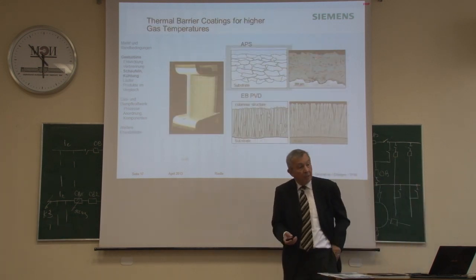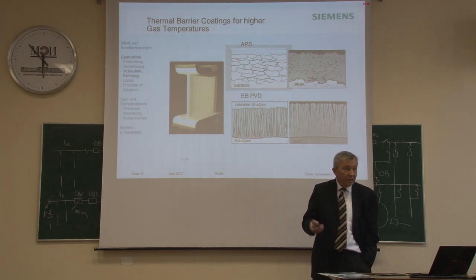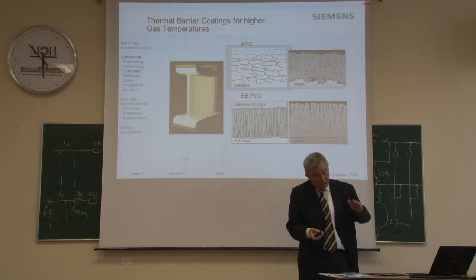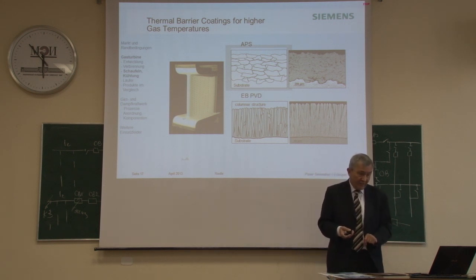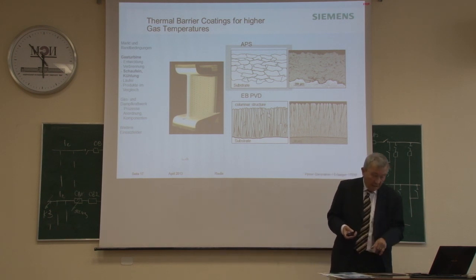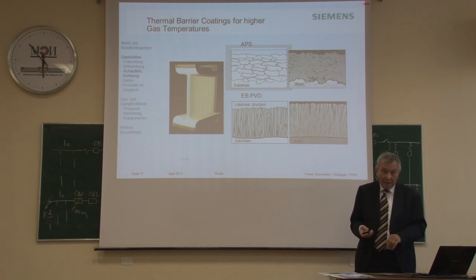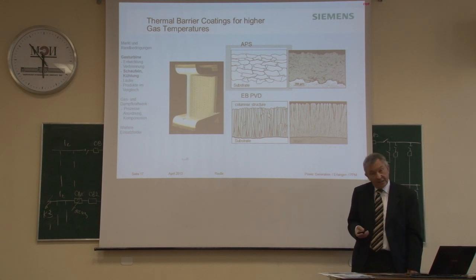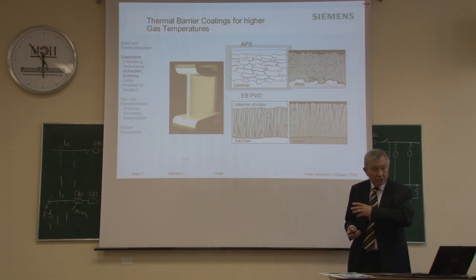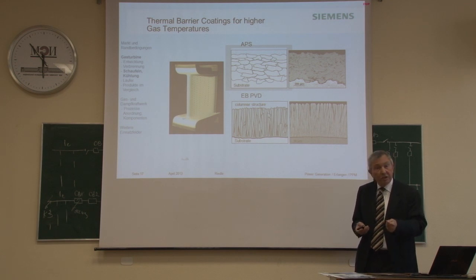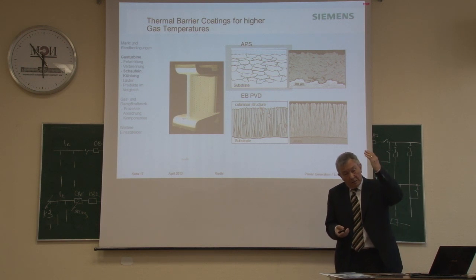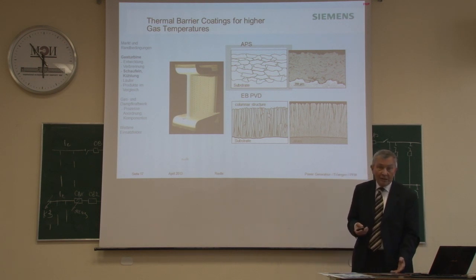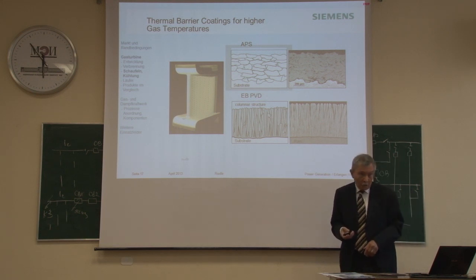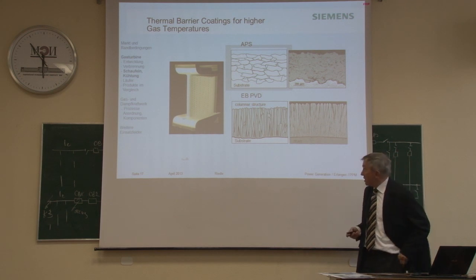One thing is better base material. The other one is you put some insulating layer, some ceramic oxides on the surface, and this reduces the temperature of the metal itself, and you do it either by spraying or some electron beam vaporization technique. Why can't we build that just half a centimeter? Again, don't forget, in operation, that ceramic layer might have 1100, 1200 degrees C, and then you shut the gas turbine off, and within 20 seconds, the temperature falls from 1200 to 400. And you can't do that often without that coating flaking off, and so you are limited in the thickness of that coating.